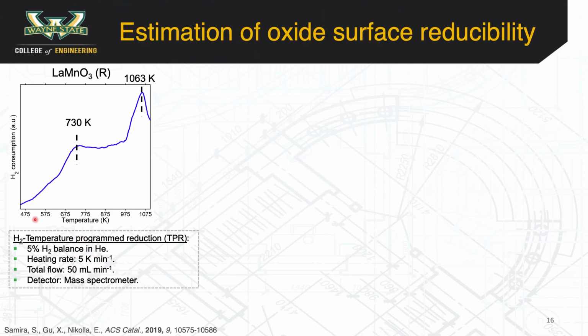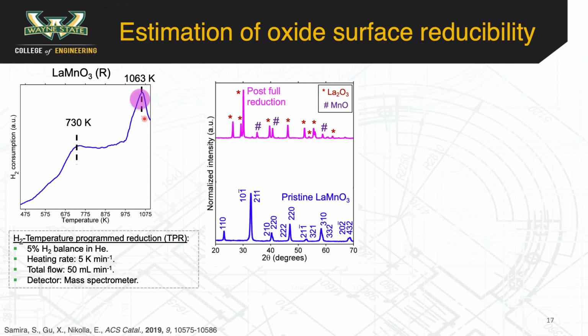The oxide is then heated all the way from room temperature to 900 degrees Celsius in our case, and the hydrogen consumption as a function of temperature is monitored. Two distinct hydrogen consumption peaks are observed, one at relatively lower temperatures of 730 Kelvin, the second one at relatively higher temperatures of 1063 Kelvin.